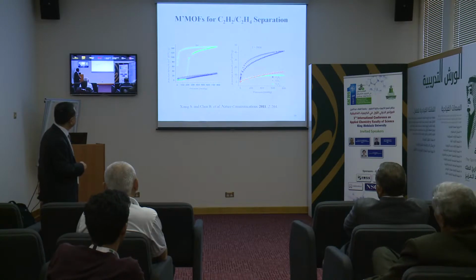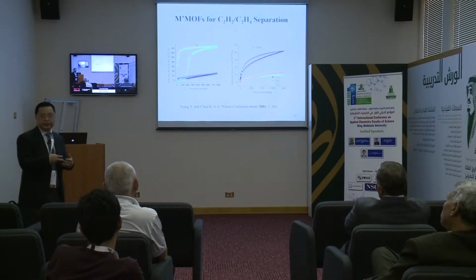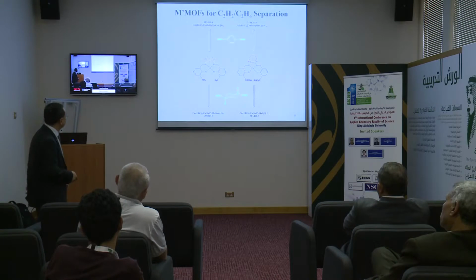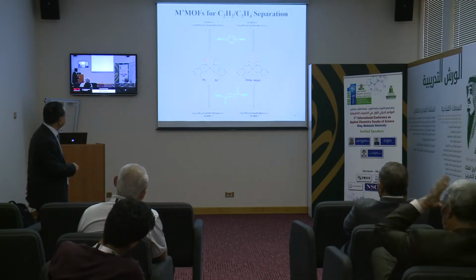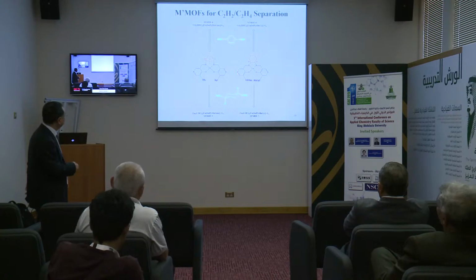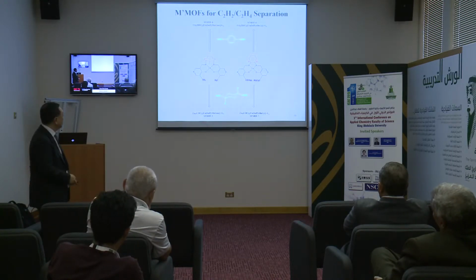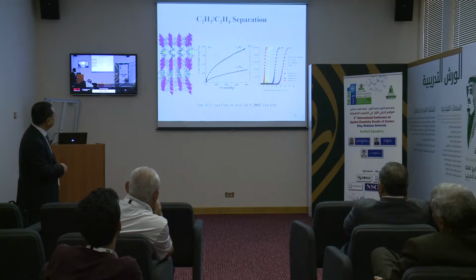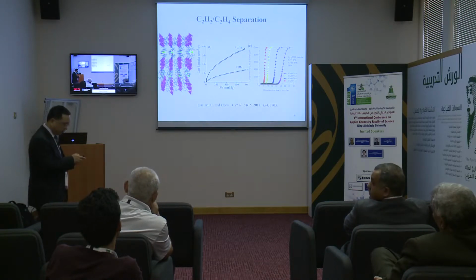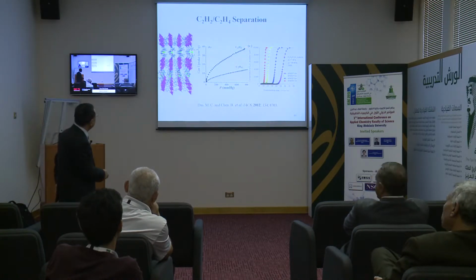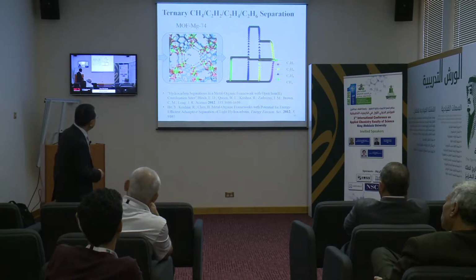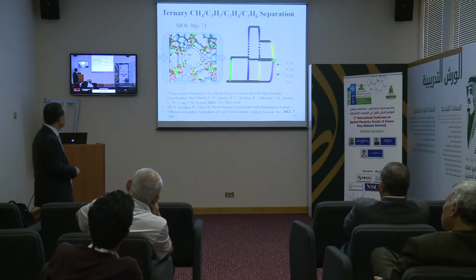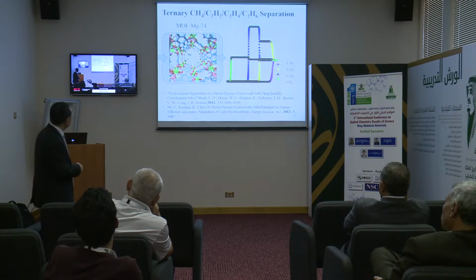And we realized the first examples of MOF materials for acetylene and ethylene separations, although here the uptake is not so high, but the selectivity is kind of high. And as we mentioned, we use different diamines, different functional groups, different carboxylates, so the pore can be tuned to optimize the separation capacity. Again, this separation selectivity is okay, but the uptake is not so high. And a little bit later than Long's work, we also realized the MOF-74 magnesium one for the separation of these four components.